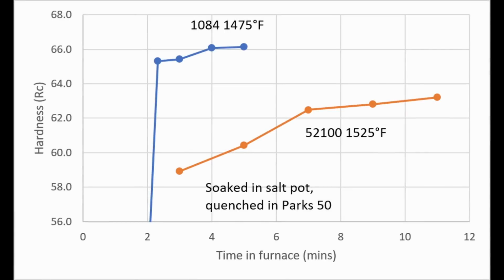Now, to illustrate what I mean with the difference between heating to the temperature versus soaking to get the carbides to dissolve, I did another experiment with 52100. So similar to my 1084 study, I used the same size coupons. 52100 has 1.5% chromium in it, which significantly slows down the time for the carbides to dissolve. I used 1525 Fahrenheit, 830 Celsius with this steel because its optimum austenitizing temperature is somewhat higher than 1084, which only has carbon, manganese, and silicon.